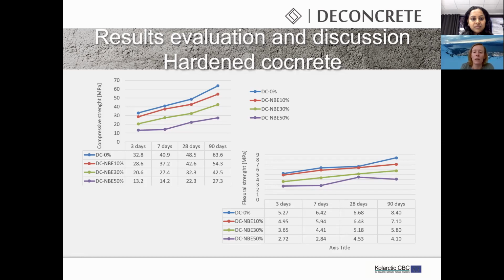And 50% replacement is a rather high replacement ratio, which had a significant impact on the compressive strength. As we are trying to implement this into the industry, a replacement of 50% might not be efficient because there is not enough sludge to put in the production. Actually, this 10% might be efficient to consume all the sludge produced in the concrete plants and still maintain the production with high quality.